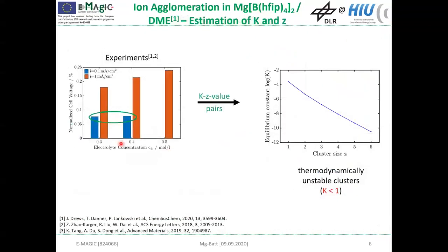So from experiments, we also know that the overpotential for a 0.3 and 0.4 molar electrolyte is almost similar at low current density, and this can be used to estimate value pairs for K and Z. And with that, we find that the equilibrium constant exponentially decreases with the cluster size. So consequently, bigger clusters need to be less stable to have the same effect on the overpotential. More interestingly, the clusters seem to be thermodynamically unstable, independent of their size.